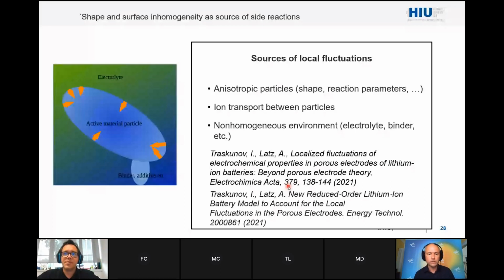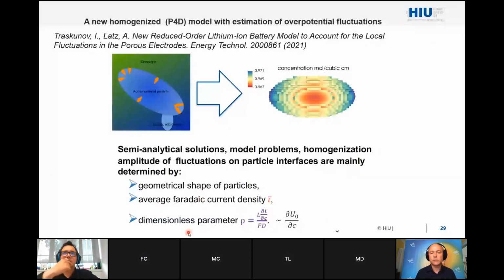And what Igor found is that there's a dimensionless parameter which has to be considered in addition to the usual parameters. This is the derivative of the Faraday current with respect to the concentration, which is proportional to the concentration dependence of the overpotential. So there is a difference whether you have LFP or whether you have LCO, or whether you are in the flat regime of the graphite OCV or in the regimes where you go from one plateau to the other. In each of the regimes, you will get different overpotential fluctuations and different probabilities of SEI growth, of plating events.